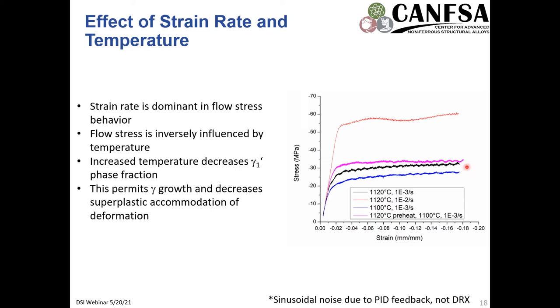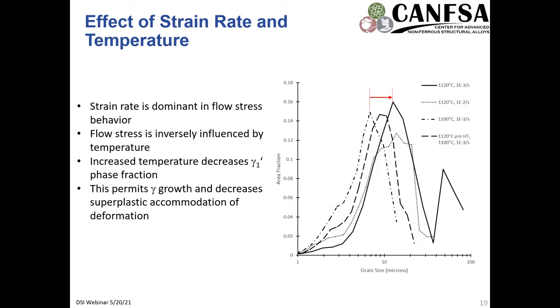And to support this, if we had a preheat treatment to further dissolve the gamma prime, but then deformed the material at a lower temperature, such as we did with the pink or purple line here, 1120C preheat and 1100 deformation at this low strain rate, then we have the highest flow stress of them all. And this is corroborated by this increase in average grain size here at 10 to the negative 3 versus 10 to the negative 2 per second. There's a secondary or bimodal grain size distribution at 10 to the negative 3. I'll go into a little bit more detail about that later on.